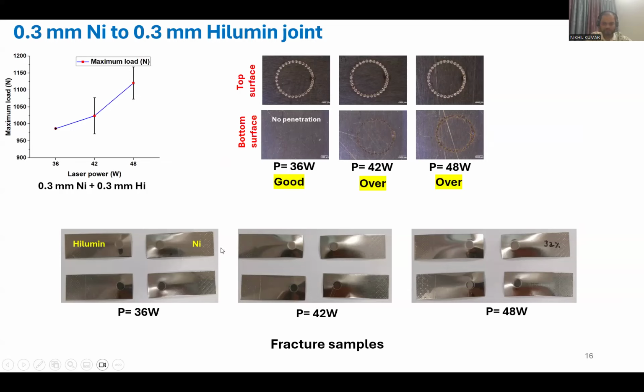So it is not always necessary to break the top sheet, because it could be possible to break it if I had made 2 or 3 circles here, because strength also depends on the weld area. I think this weld area was not sufficient to break the top sheet. If I had made 2 or 3 circles instead of only 1 circle, I would have broken these samples as well. So I have concluded here because there is no bottom sheet penetration, and this is interfacial failure, but still we have very high strength. This is about 1000 Newton load. I think about 100 kg load can survive with this tiny 0.3 millimeter nickel sheet.